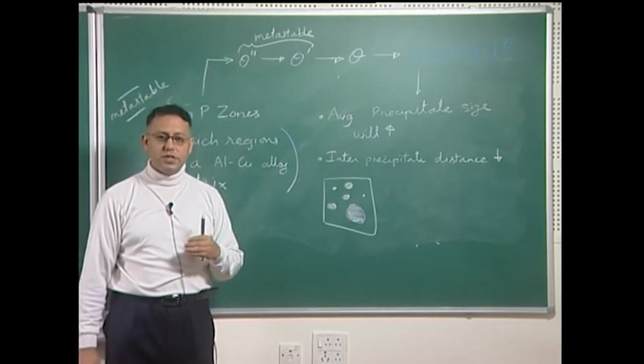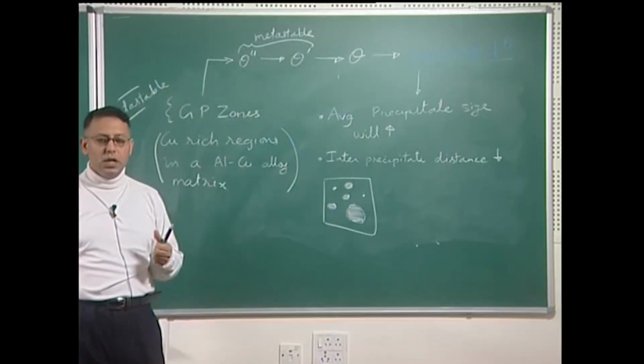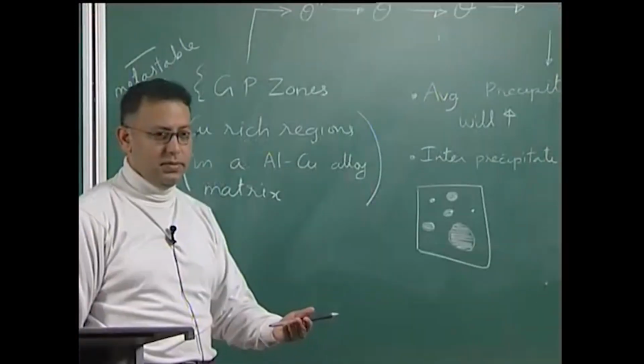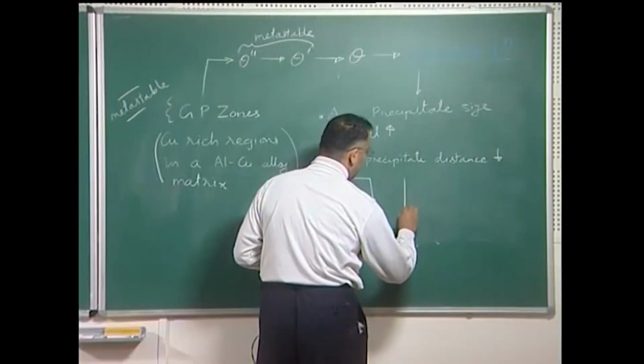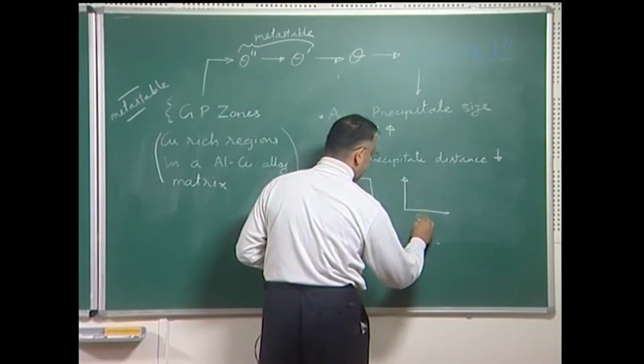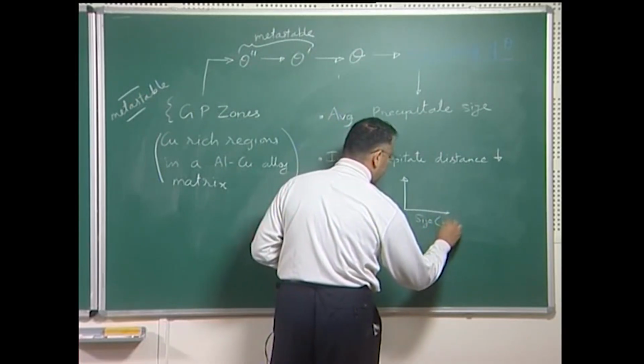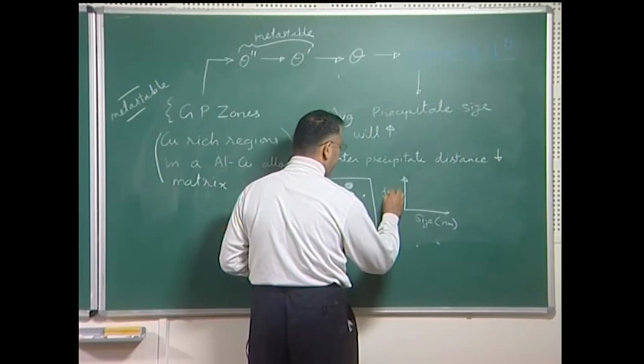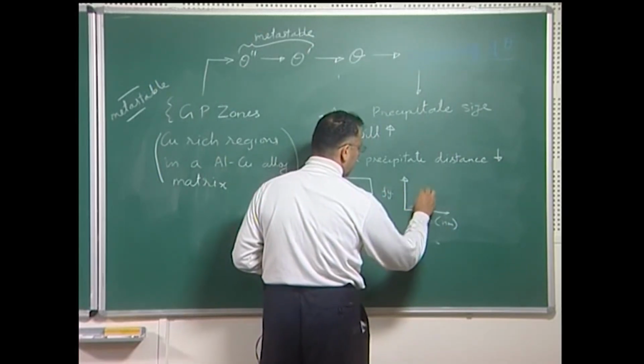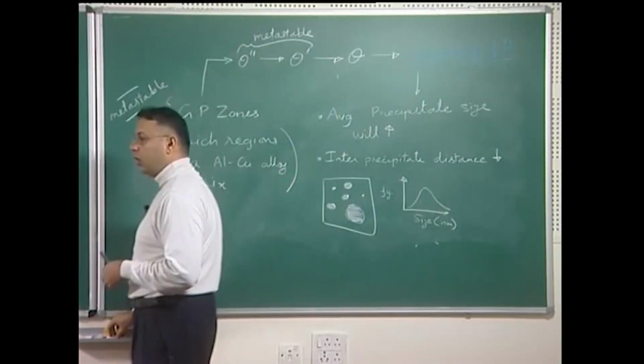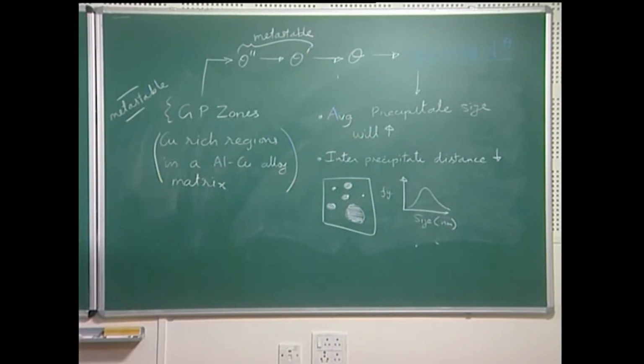So, when I am talking about distribution of phases, I am talking about the spatial distribution of sizes and the frequency of occurrence of various sizes. Therefore, you can plot at some point of time the size, which could be measured in nanometers, for instance, and the frequency, and you can see a variation which could also be thought of as a distribution of sizes. So, I need to worry about the spatial distribution of the second phase, the connectivity of the second phase, the frequency of occurrence of various sizes, and also the shape of these second phase particles.